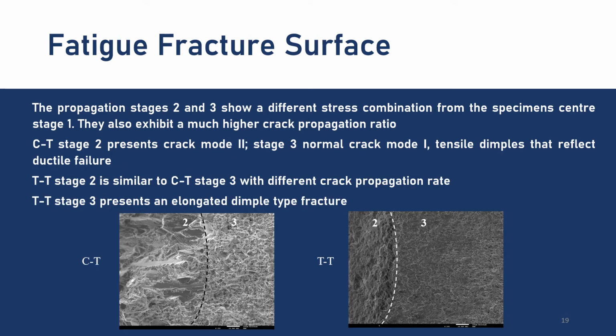Now, after stage 1, there are stages 2 and 3 with completely different fracture surface morphologies. Looking first at the CT, stage 2 presents crack mode 2, and stage 3 presents crack mode 1 with tensile dimples that reflect a ductile failure. Stage 2 of the TT is very similar to stage 3 of the CT with the tensile damage dimples, while TT stage 3 presents elongated dimple type fracture associated with shear damage.